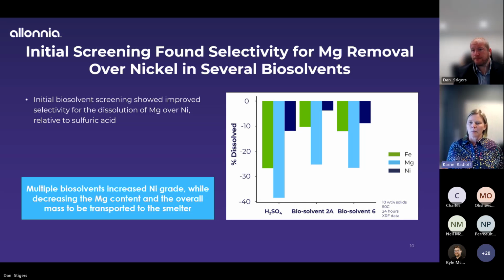Now, what we can see pretty quickly is the sulfuric acid did a good job of dissolving out a lot of the magnesium and a little bit of the iron, but it also solubilized a lot of the nickel. And that is not what we want. The problem with sulfuric acid is it's not a selective solubilizing, it's kind of targeting all of the minerals. And it further has the drawback of it's not recyclable. The sulfuric acid in this type of reaction is consumed.